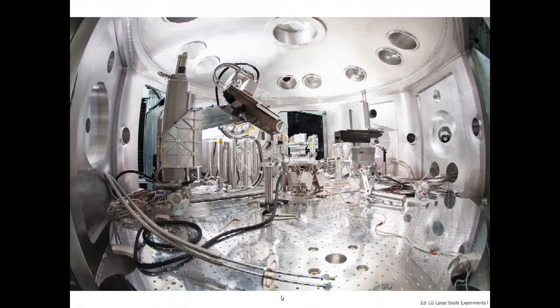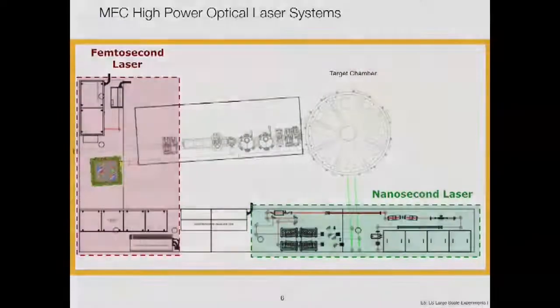So here, as an example, you see 2 X-ray scattering spectrometers, which are used to look at mostly elastic scattering and mostly inelastic scattering, I should say, from the samples we create with our optical lasers. So the 2 optical laser systems we have, in our hutch we have these big optical enclosures with 2 laser systems, a very short pulse laser system and a more energetic, longer pulse system.